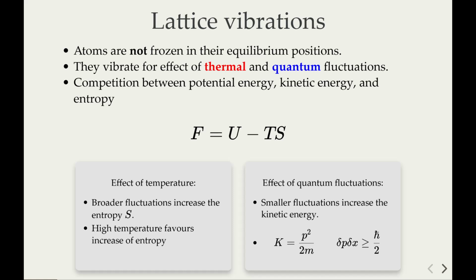You immediately see that if the temperature is not zero, there is an extra contribution to the free energy, which is entropy. Entropy usually wants to spread the probability distribution of your ions—the larger the probability distribution, the higher the entropy. So the higher the temperature, the higher this contribution wants to be. Temperature tends to increase vibration for this reason.